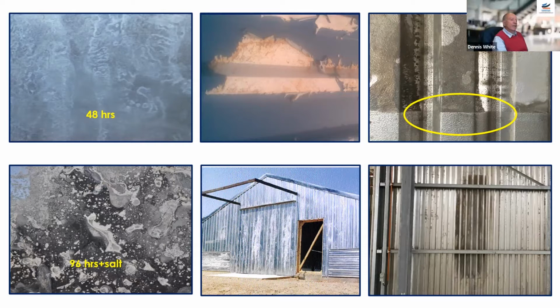Dennis, off you go. Okay, another thing that people don't normally understand is that polycarbonate products are equally vulnerable to wet storage damage. The polycarbonate itself, if it's exposed to water for any length of time and some high temperatures, will soften, and you can also get the UV protective layer delaminating from the product. So if you read the brochures from the manufacturers, they caution you against storing the stuff out in the open or under a clear plastic surface or anywhere where you're going to get moisture trapped, and we'll discuss how to wrap and protect the materials as we go along.